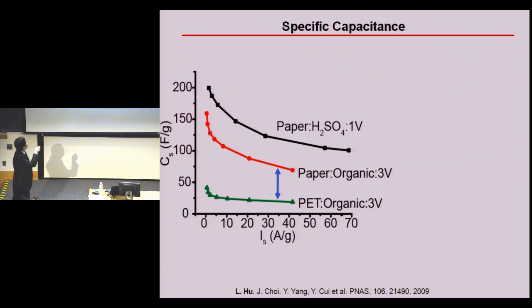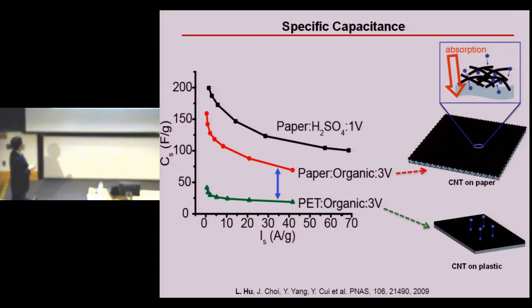So based on this kind of simple measurement, I show you here the specific capacitance of the supercapacitors at different current densities for the paper-based device compared with PET or plastic-based devices. We can see here, due to the highly porous structure of conductive paper, we get much higher capacitance compared with plastic-based ultracapacitors. This is due to the porous structure, with porosity at different scales.